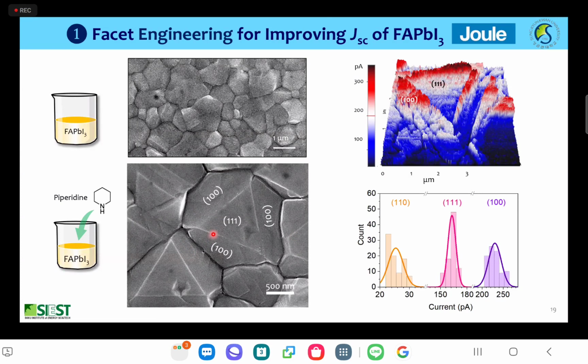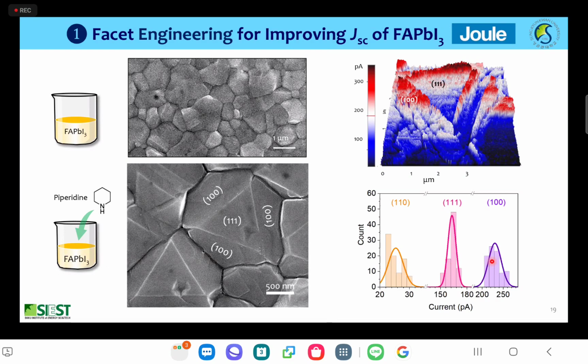So we prepared the crystal facet enhanced perovskite film using the piperidine additive. This is the conventional method, and you cannot figure out a distinct crystal facet. But using the piperidine additive, we can produce the 100 and 111 crystal facets. Interestingly, from the photocurrent AFM measurement, we found that the 100 has the highest photocurrent density, and the 111 crystal facet also shows high photocurrent density close to the 100 crystal facet. However, the 110 crystal facet shows pretty low photocurrent. Therefore, you have to avoid producing the 110 crystal facet facing toward the sunlight.